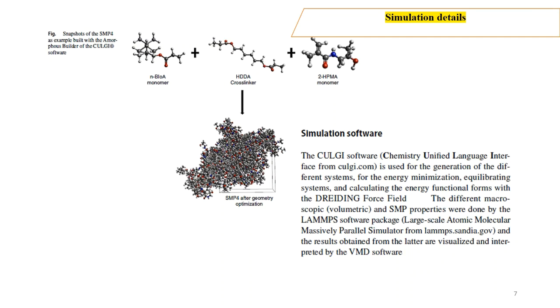In the simulation part, the CULGI software is used for the generation of the different systems, for the energy minimization, equilibrating the system, and calculating the energy functional forms with the Dreiding force field. The different macroscopic and shape memory properties were computed by the LAMMPS software, and finally the results obtained from the latter are visualized and interpreted by the VMD software.